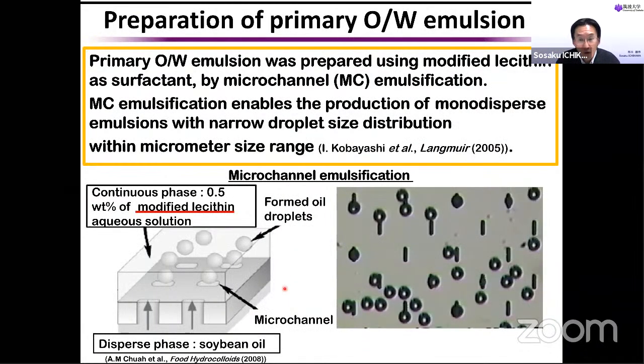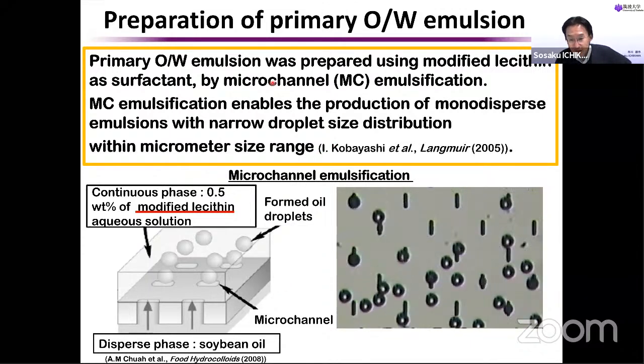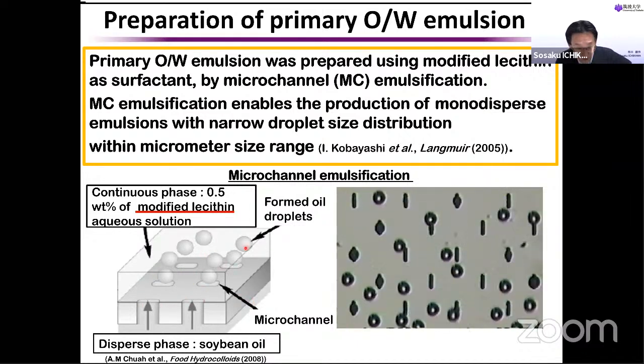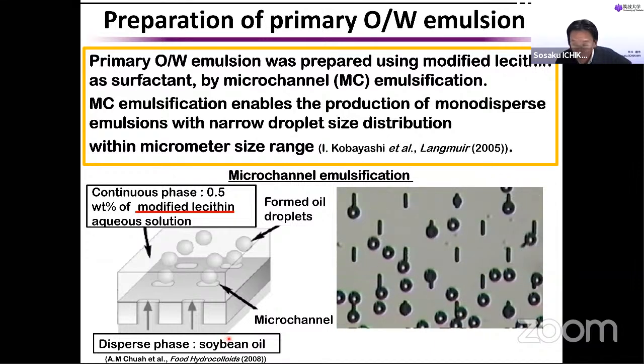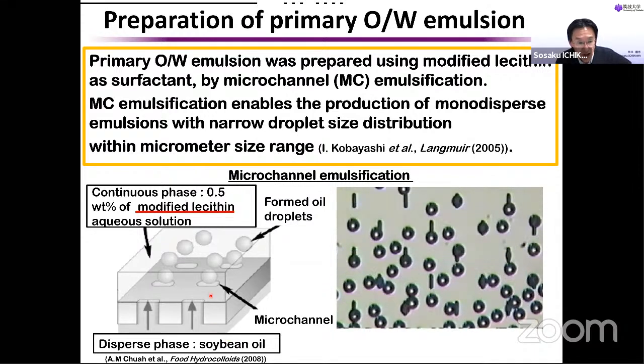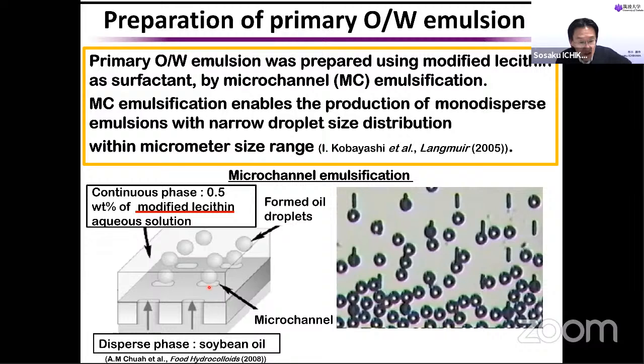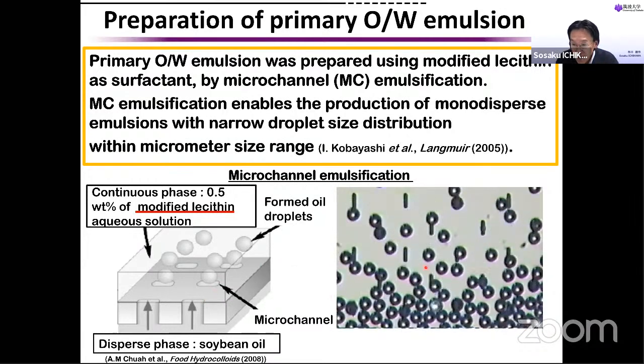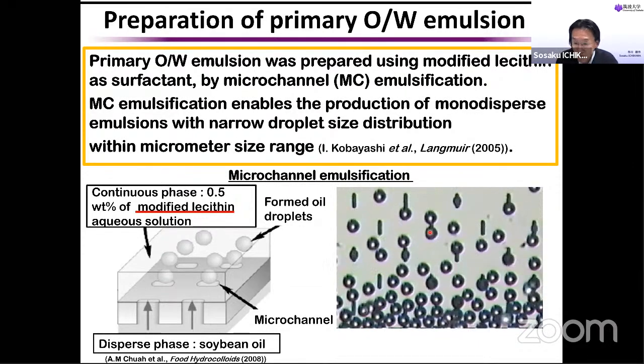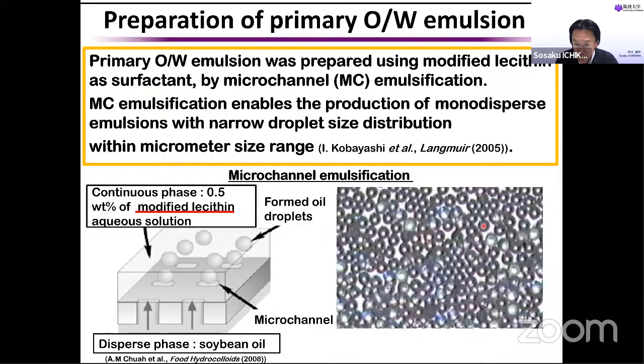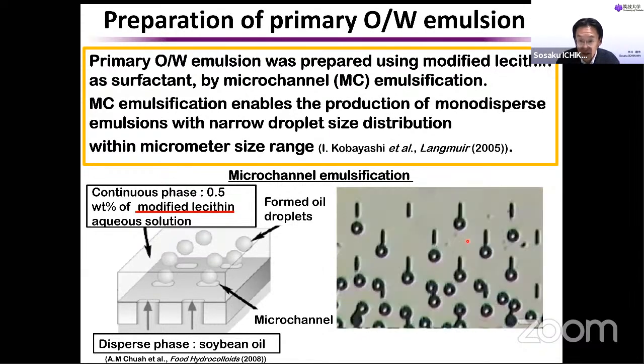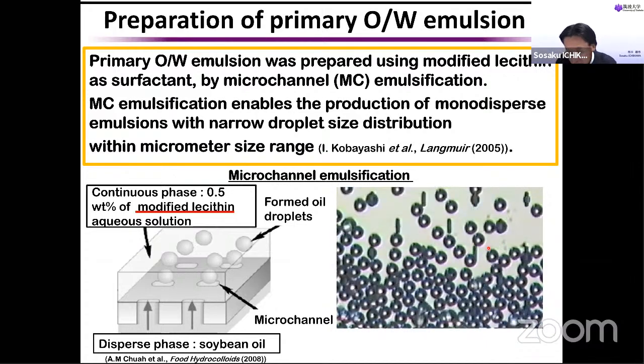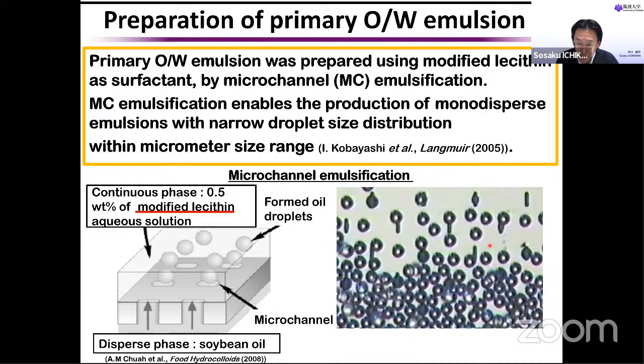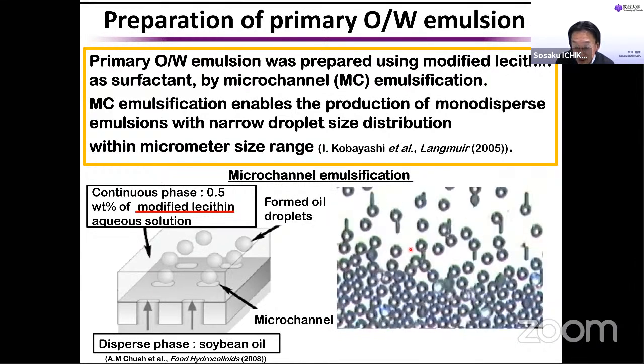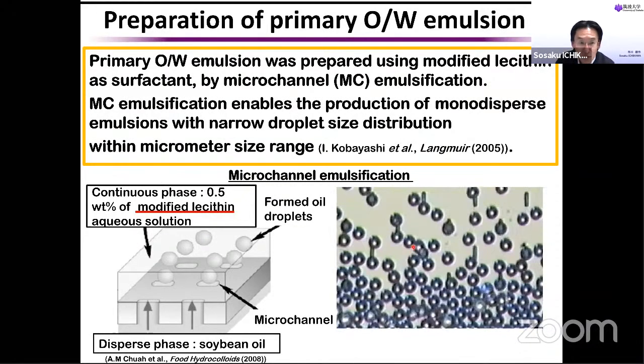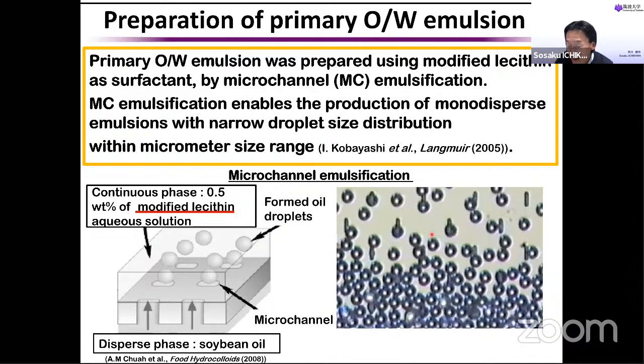Firstly, we prepare the oil droplet using microchannel technique. This is an illustration of microchannel. We push out the soybean oil as an oil phase through this channel. This channel is made by silicon etching. So then you can see we can get very uniform soybean oil droplet through this microchannel. This is the oil droplet made by this microchannel emulsification. This is a very unique technique to make very uniform oil droplet. Using this uniform oil droplet, we try to modify the surface of this oil droplet by layer by layer technique.